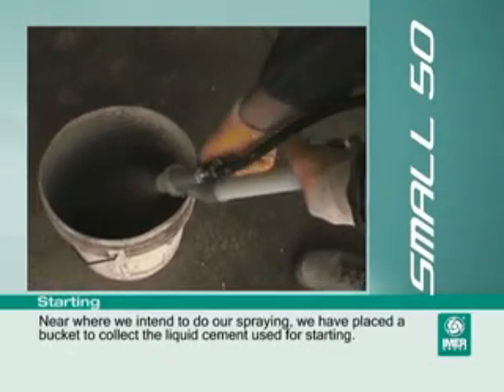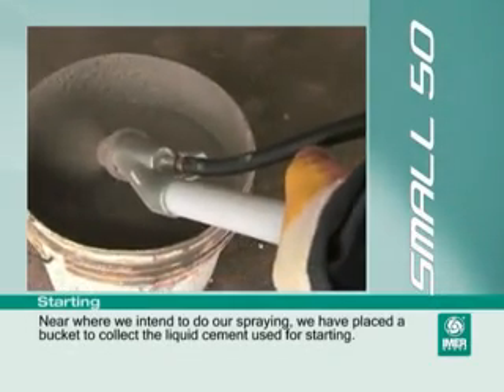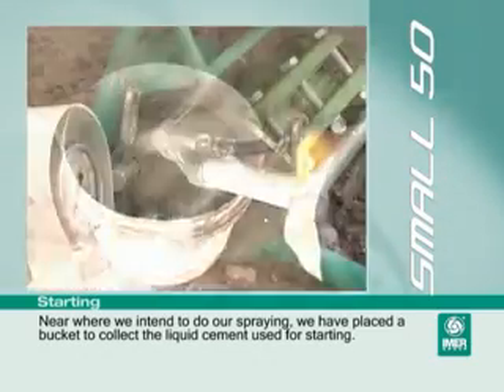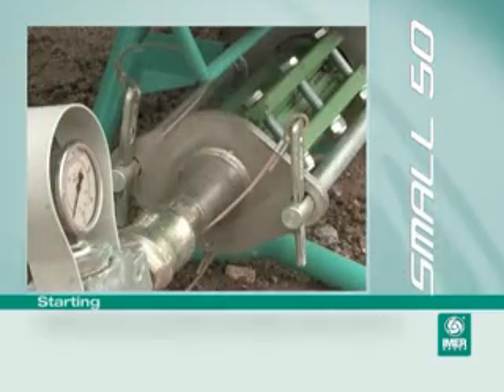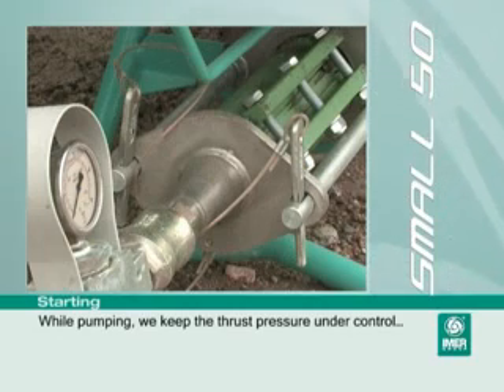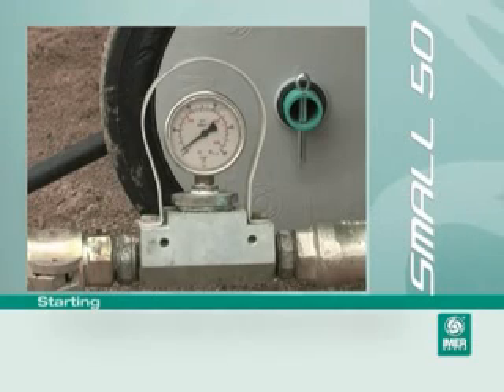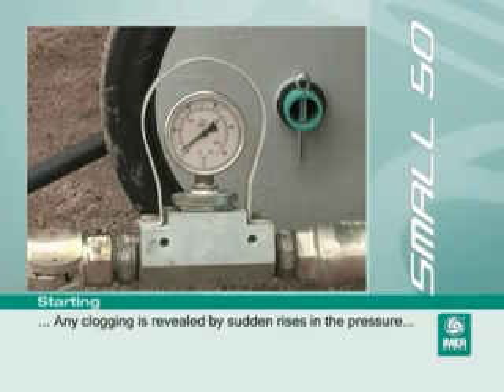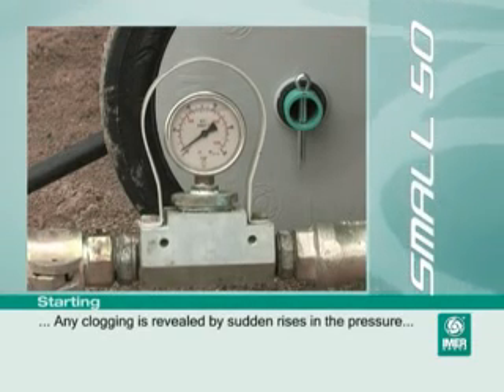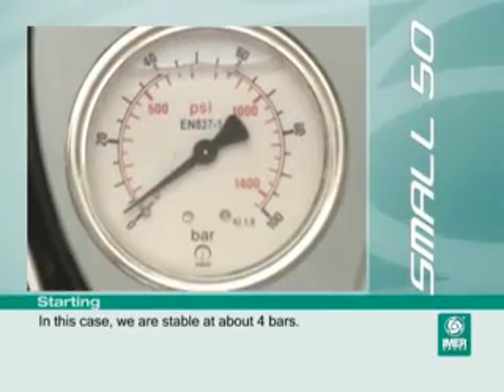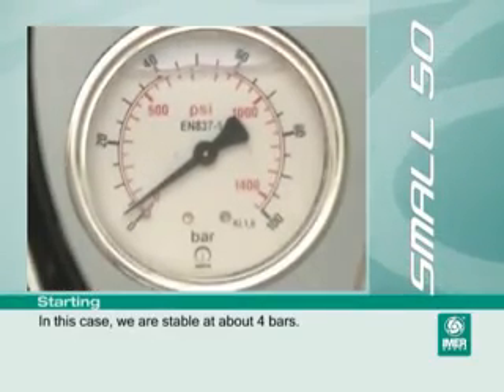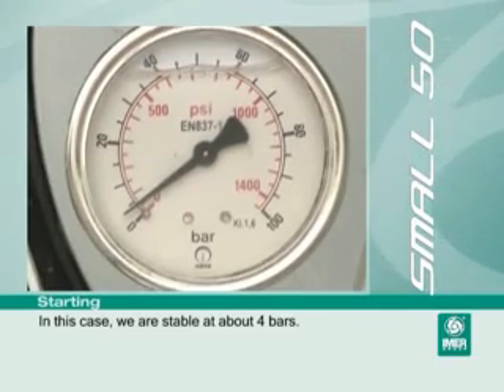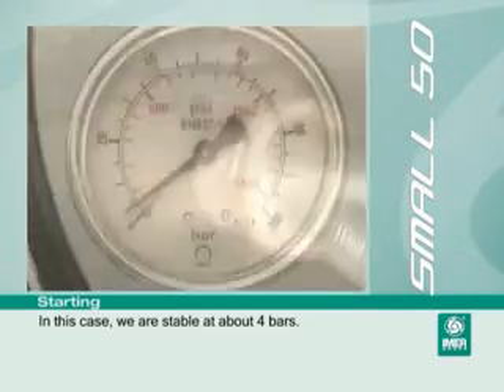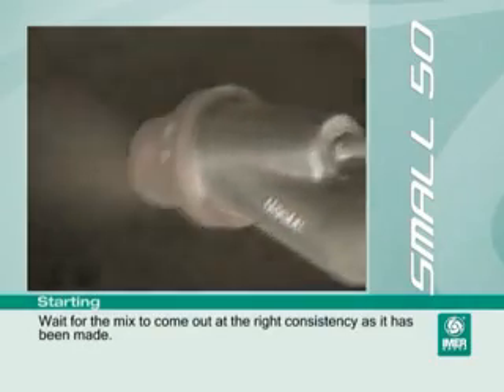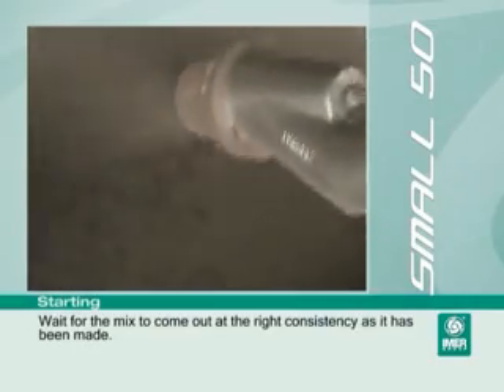Near where we intend to do our spraying, we have placed a bucket to collect the liquid cement used for starting. While pumping, we keep the thrust pressure under control. Any clogging is revealed by sudden rises in the pressure. In this case, we are stable at about 4 bars. Wait for the mix to come out at the right consistency, as it has been made.